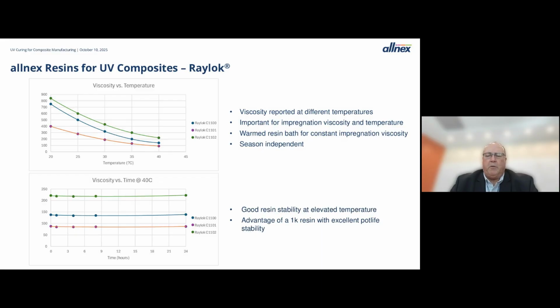And the other aspect we mentioned was that photoinitiators don't react with heat. They only react with UV. So the bottom chart shows viscosity versus time. So we held everything at 40 degrees C and followed the viscosity. And you see there's virtually no difference in viscosity. There's no viscosity creep, no viscosity gain over a 24-hour period. And that's, again, due to the fact that photoinitiators react to UV energy and not thermally.